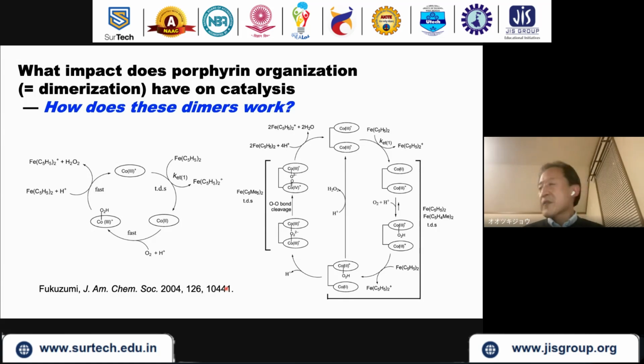Why is the dimer efficient? Some researchers proposed a mechanism of the dimer, and I won't go into details, but basically, the dimer structure has a special environment for the substrate. If you attach a water molecule, an oxygen molecule is coordinated here. There is another coordination site very close to the one that is coordinated, so that these bridge structures can be formed, and then the reaction pathway is affected dramatically compared to the monomeric structures. That's the reason for higher selectivity towards certain reactions.